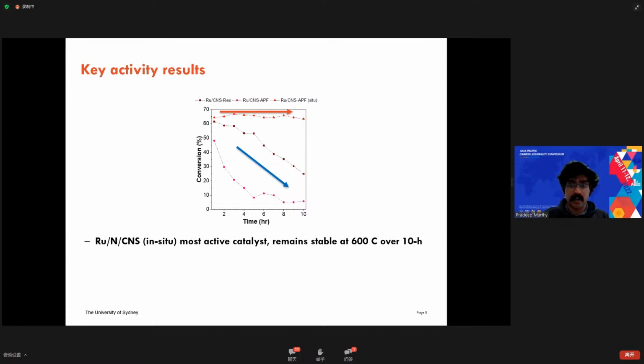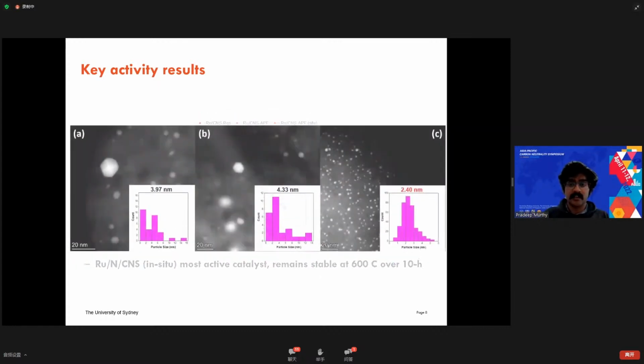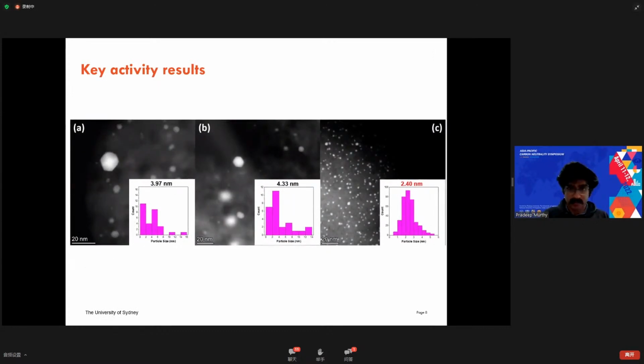To further confirm why this was the most active, by conducting a TEM analysis post-stability, we can see that the ruthenium catalyst remained quite dispersed.